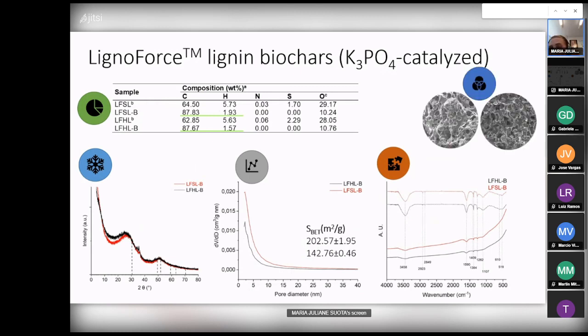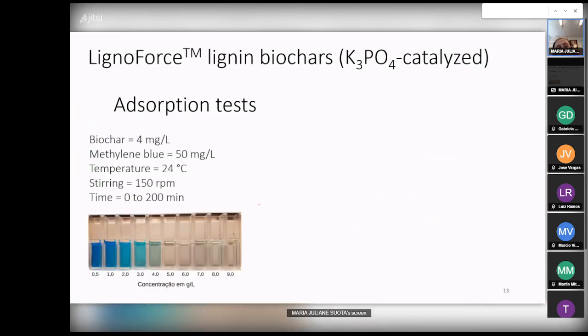And finally, after scanning electron microscopy, we could see the pore structure of this material. And we can identify here several holes and irregularities, and this is indicative of good adsorption properties. After this characterization, we went further and decided to test the adsorption capacity of those biochars. We have chosen methylene blue as a model molecule. And here, down here, we can see how efficient it was: a lower concentration of biochar is able to remove almost all the molecules of the solution,